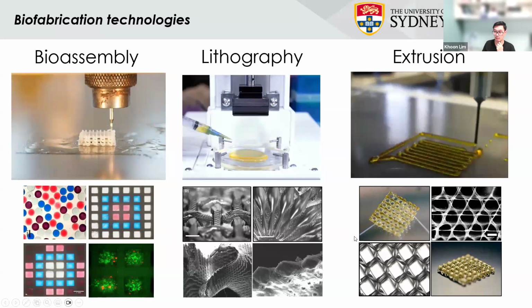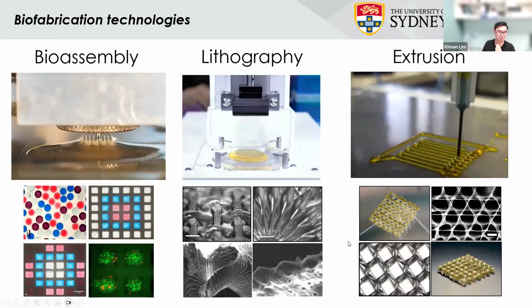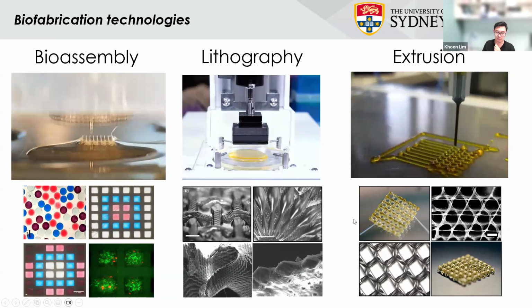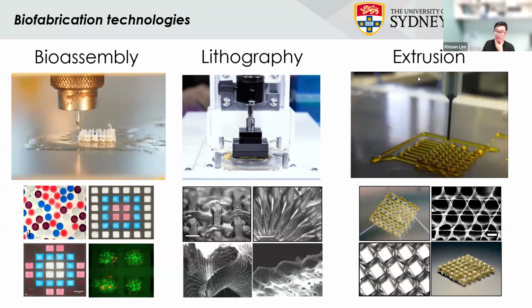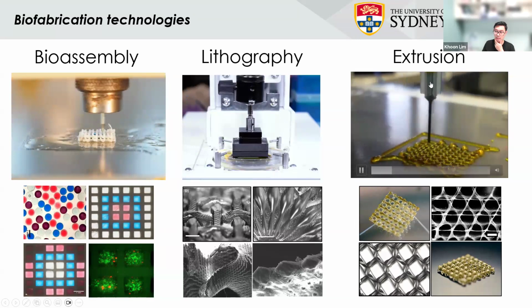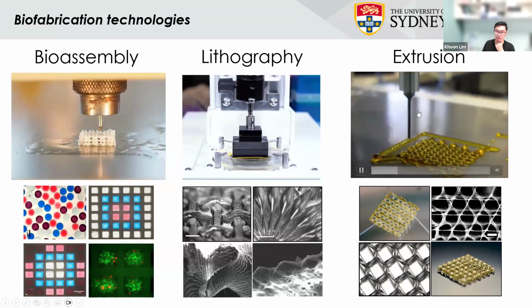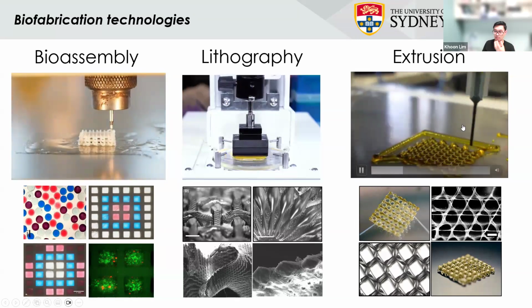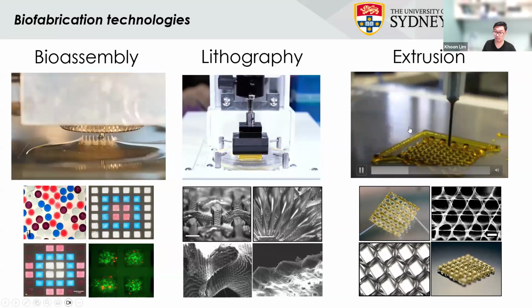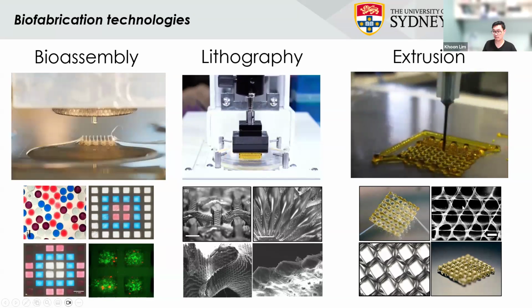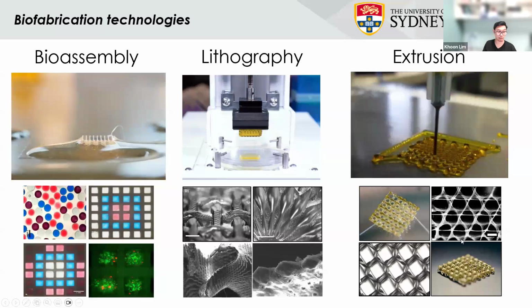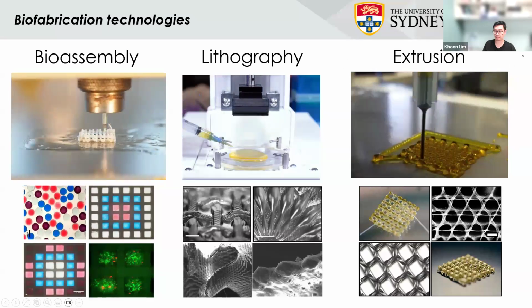And extrusion is one that is the most conventionally used. So most of the labs that work in the bioprinting space would have an extrusion bioprinter, and you're really looking at putting hydrogel material and then exerting pressure. You can push them out. You can form some really nice filaments, and you can stack them as well. And you can also have gradient structures in this case.